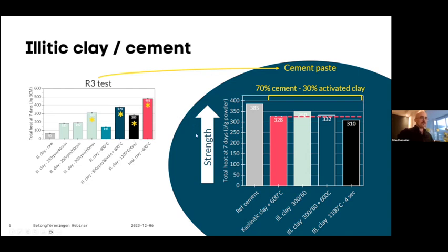In gray here is the value corresponding to the reference cement, so only cement, no clays. The pink will be for the kaolinitic calcined clays, and all the others for illitic clays with the different treatments, MCA plus calcination, and the flash calcination. So it's quite clear that in every case, we are actually very close to what we could reach with kaolinitic clays, even higher in certain cases.